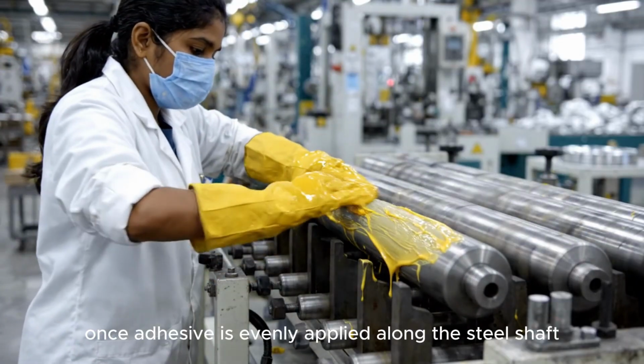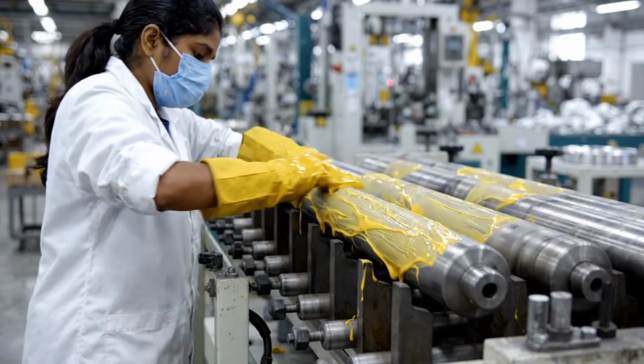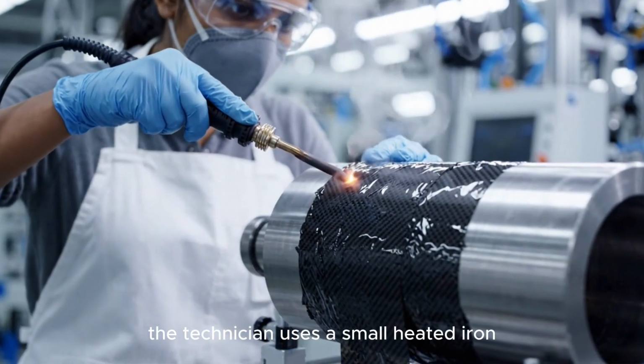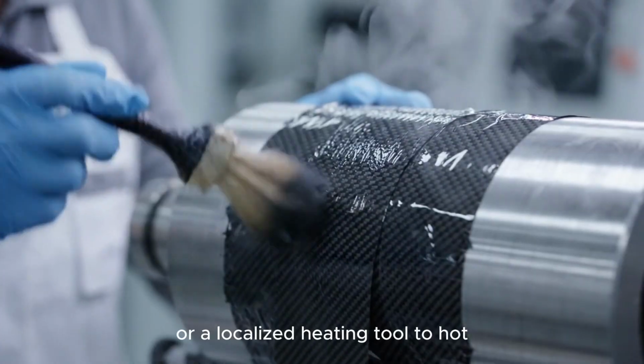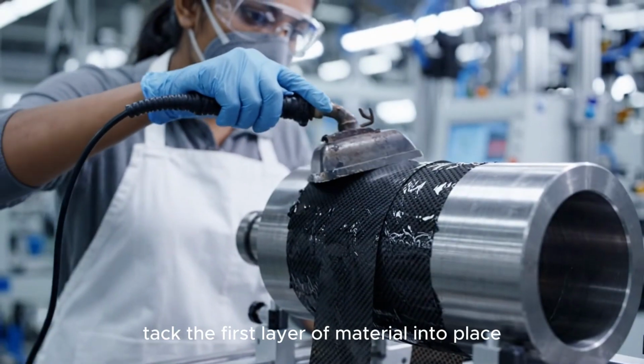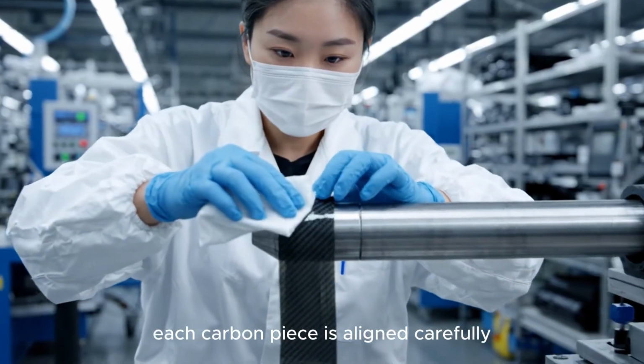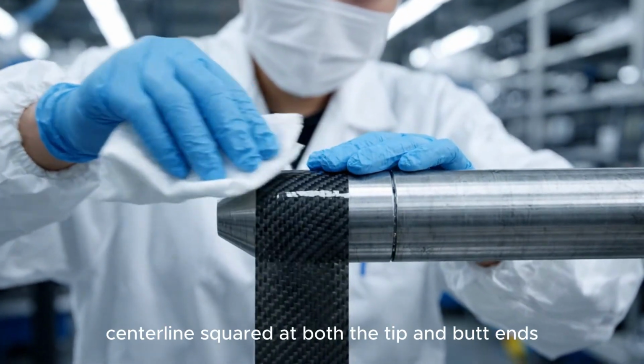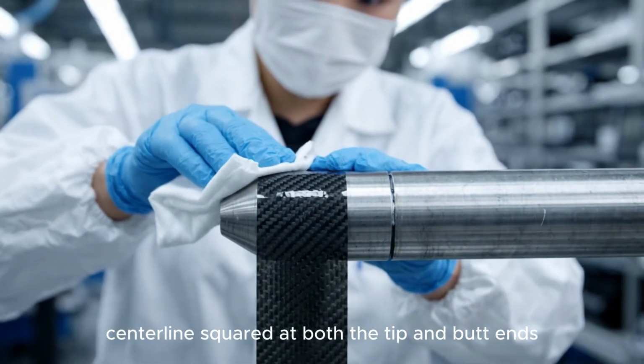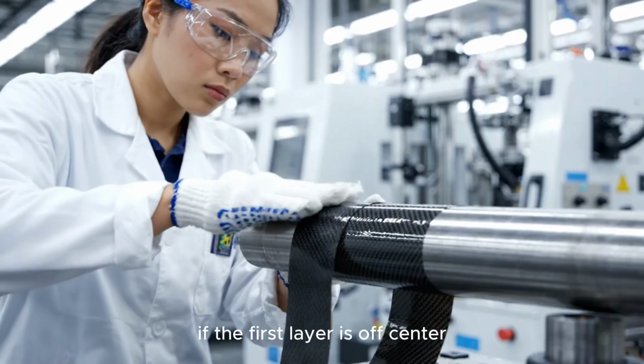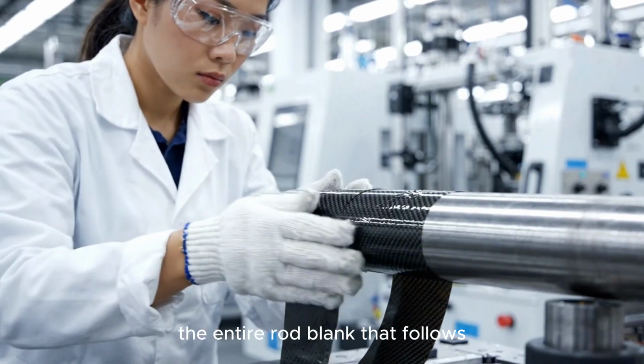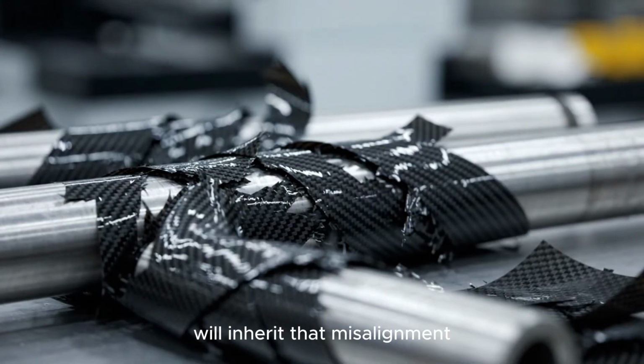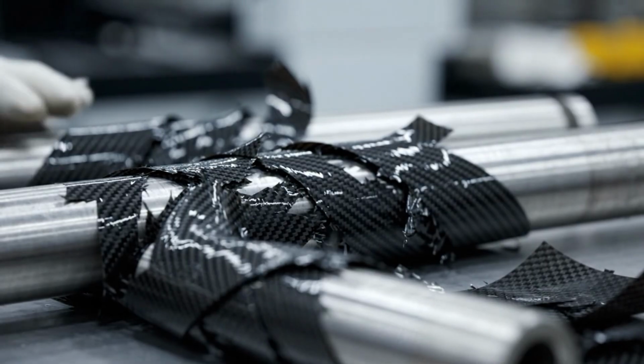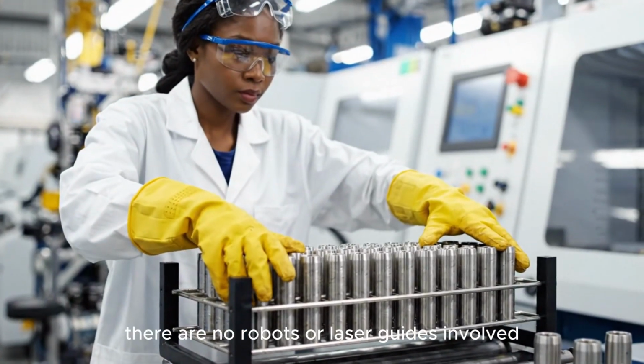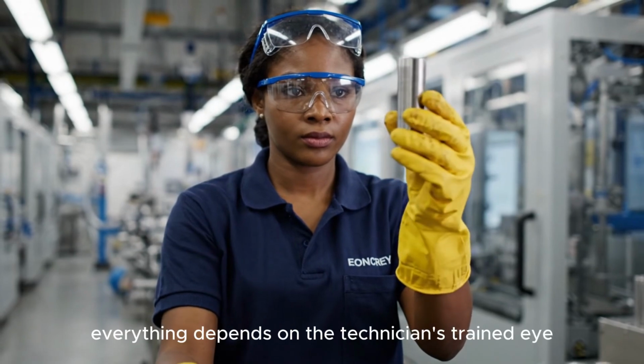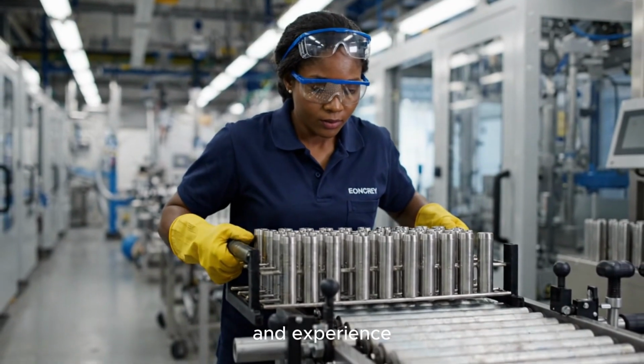Once adhesive is evenly applied along the steel shaft, the technician uses a small heated iron or a localized heating tool to hot tack the first layer of material into place. Each carbon piece is aligned carefully along the mandrel's center line, squared at both the tip and butt ends, and only then secured. If the first layer is off-center, the entire rod blank that follows will inherit that misalignment. There are no robots or laser guides involved at this stage. Everything depends on the technician's trained eye and experience.